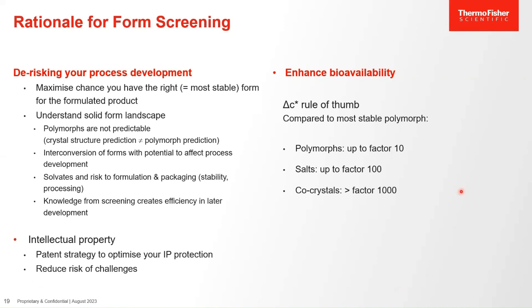And having the right form also helps to optimize and possibly enhance bioavailability. The most stable solid form may not be suitable due to poor bioavailability, and then you might start looking for salts, for example. You may be looking for co-crystals, and as a rule of thumb, different polymorphs usually have solubility differences in a range of about factor 10 in comparison to the most stable polymorph. You can increase the solubility of your API using a salt by at most a factor of 100. And for co-crystals, a factor greater than 1,000 is often mentioned. Whether this is accurate or not is a different matter. But this gives you an idea of how you can make use of solid form screening to identify a better form for your molecule.